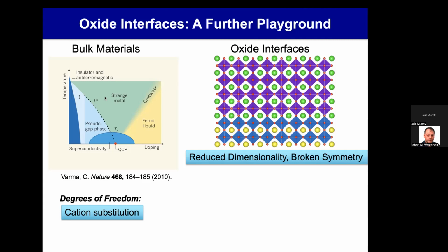For a lot of the materials that we're working with, these materials are very strongly bound in all three dimensions. It's not possible to rip a sheet of atoms off, because they aren't van der Waals materials like graphene. But because they're really strongly bound in all three directions, we can instead put just one plane of atoms down on a substrate and construct this two-dimensional layer, this two-dimensional material, in a material where one could not get that from a top-down synthesis approach. So you could think about broken symmetries or reduced dimensionality in all kinds of materials, even ones that don't want to form this monolayer structure like graphene.